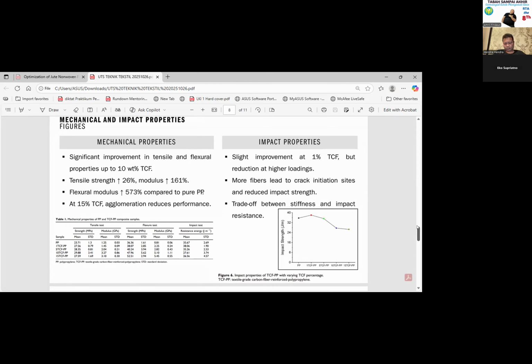So the trade-off is clear. While more fiber increases stiffness, it can also reduce the toughness. In design terms, this means that if you are producing a component that needs both stiffness and impact resistance, like an automotive interior, you might choose a moderate fiber content, maybe around 5 to 10%, depending on the required performance balance. This is a great example of how material science is often about compromise and optimization, not just about maximizing one property.